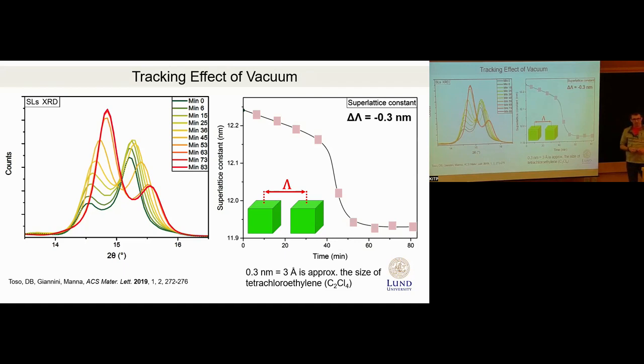Yes. And then, can you tell how much solvent you have left? No, that we cannot tell. We just see that nothing happens. Could you reasonably conclude that there is no solvent left? No, we could not. When you talk about solvent, here the solvent is the one from which the self-assembly was performed, tetrachloroethylene. But then nanocrystals themselves came from the synthesis in a long-chain solvent, octadecane, which is also, we suspect, still present in the sample. So we think of them as different solvents. So here I cannot tell that all solvent is removed yet, because I'll show the data when we start heating them up. So we subject them to vacuum and then we heat them up and we still see contraction, which might be further explained by escaped solvent.